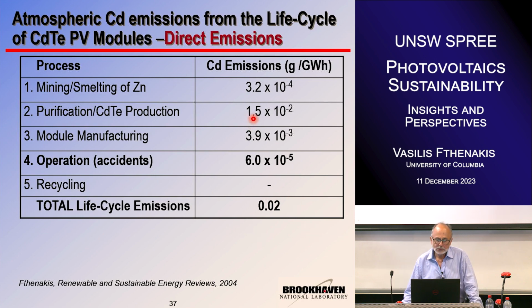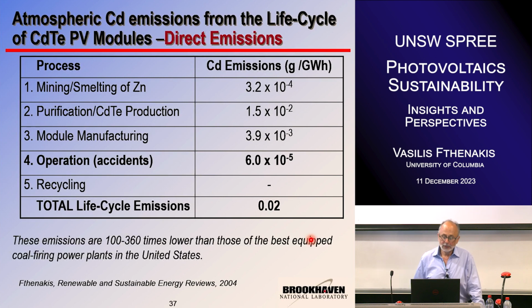Most of the emissions of cadmium in the life cycle occur during purification and production of cadmium telluride. If normalized per gigawatt hour of production, and this corresponds, I think, to about 12% efficiency, now we have 18.3% efficiency, so the numbers are better, there are only 0.02 grams per gigawatt hour. And these emissions are 100 to 360, now even higher, times lower than those from the best equipment in United States coal power plants.